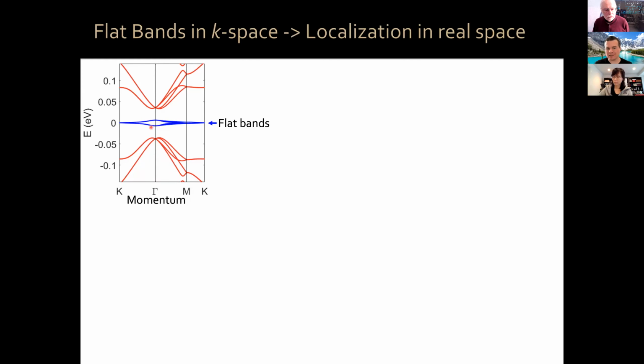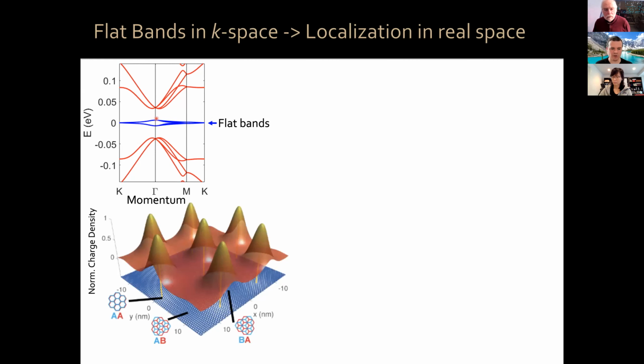Now, flat band in momentum space, okay, what happens when we place electrons in those flat bands? Where do they like to go in real space? So remember, to go between momentum space and real space, you have to do a Fourier transform, okay? A Fourier transform of a flat object is a highly peaked object, okay? So if you look at where the electrons like to go when you place them in these flat bands, they like to go in regions where locally the registry between the 2 graphene sheets is such that all of the carbon atoms in layer 1 are underneath the carbon atoms in layer 2, okay? We call those regions AA stacking, and there is where the electrons like to sit, okay?